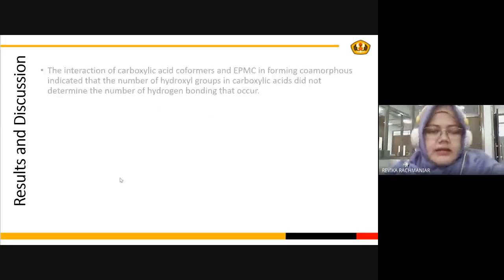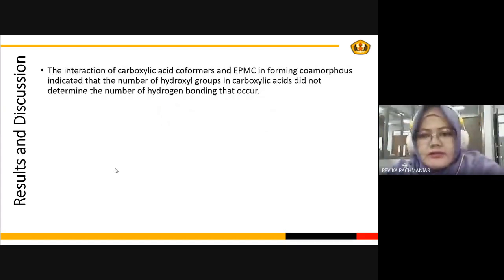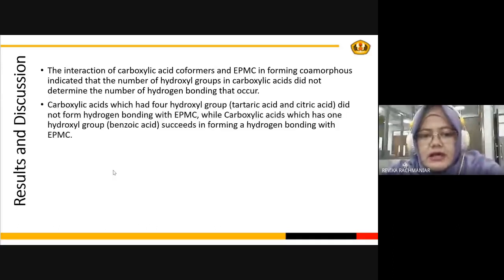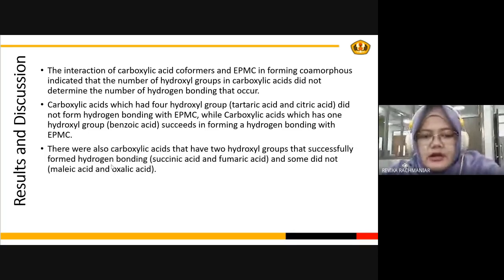The interaction of carboxylic acid coformers and EPMC in forming coamorphs indicated that the number of hydroxyl groups in the carboxylic acid did not determine the number of hydrogen bonds that occur. Carboxylic acids which had 4 groups did not form hydrogen bonding with EPMC, while a carboxylic acid which has 1 hydroxyl group succeeded in forming a hydrogen bond with EPMC. There were also carboxylic acids that have 2 hydroxyl groups that successfully formed hydrogen bonds, like succinic acid and fumaric acid, and some did not form hydrogen bonds, like maleic acid and oxalic acid.